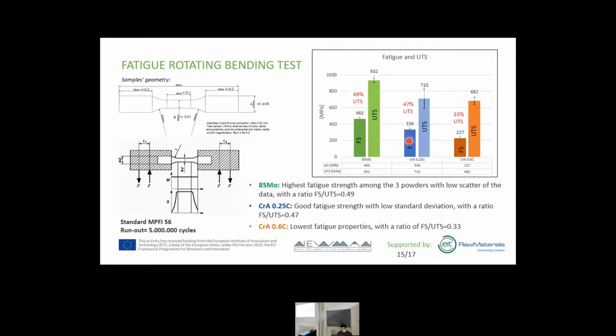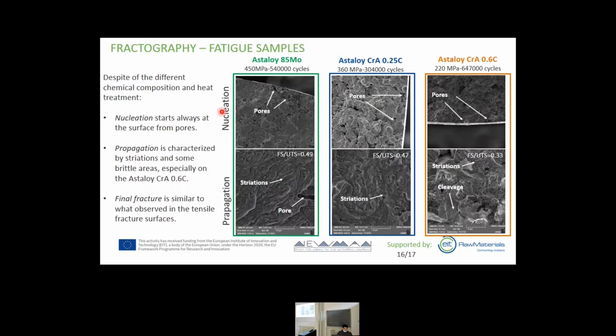the fatigue results are characterized by a low standard deviation. And the second one is that the ratio between the fatigue and tensile strength of these first two powders is about 50%, while the last powder shows a ratio of about 33%.